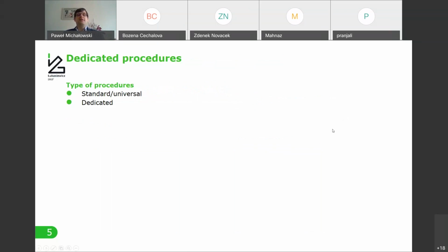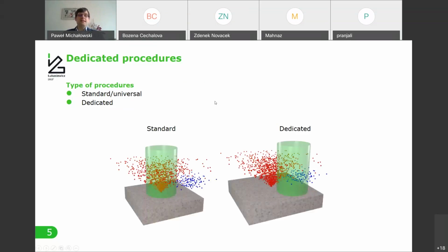So basically, when I compare it to standard procedures, a standard procedure is typically optimized in such a way to maximize the total number of detected ions, as shown here. So this green cone represents the ions which are collected. But if you look at this, this is especially true for high incident angle bombardment, that various types of ions may have a very different spatial distribution, the sputtering directions. So if we want to consider other types of atoms, which I mark here in blue, as you can see, there is just a few of them that can be detected in such a way.